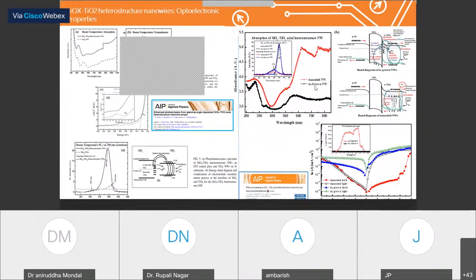And this kind of material is then very much applicable for the photodetector. So we have seen the photodetector, which is annealed, is more responsive than that of the as-deposited samples. So these samples show different new kinds of transitions between the conduction band and the valence band, which has been described here.